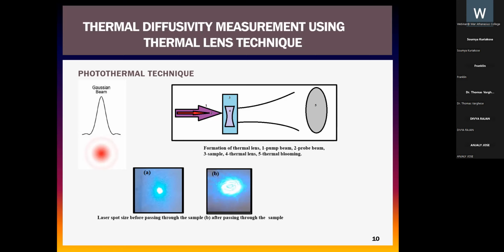A Gaussian beam, that is a laser beam, is incident on a sample, which will excite the sample, resulting in non-radiative relaxation. Thus, heat will be generated inside the material, which is found to be maximum along the axis of the cylindrical beam waist. As a result, the temperature generated will force the molecules of the material along this axis to move towards the periphery. The spreading of molecules results in a change in the refractive index, which will result in the formation of a lens-like optical element termed as thermal lens. If a concave lens is formed, we can observe a thermal blooming through a detector. This can be used to investigate the thermo-optic properties of the sample, which is called the thermal lens technique.